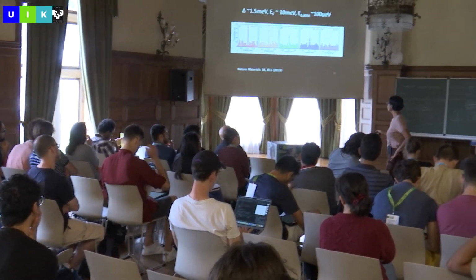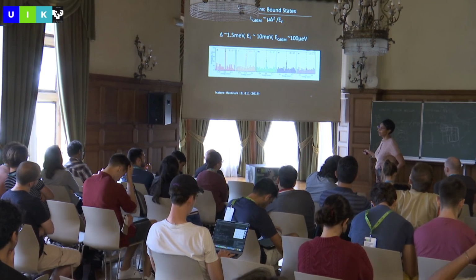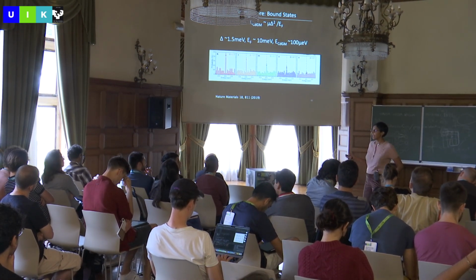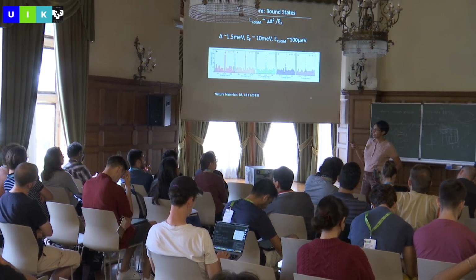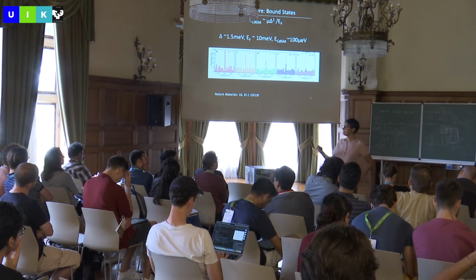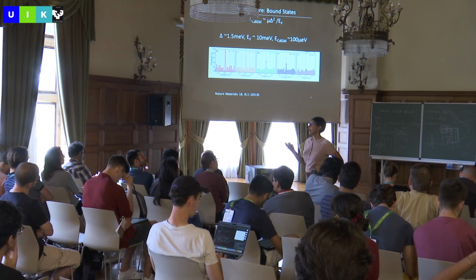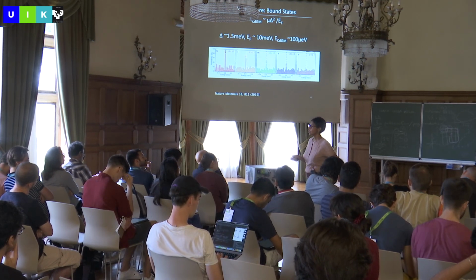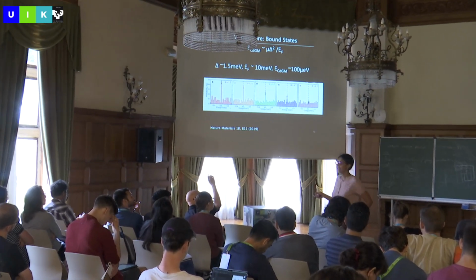So what they found was at not very low magnetic fields, fields like 1 Tesla, 80% of the vortices showed zero bias peaks, okay? And then as you increase the magnetic field, the number of vortices that show zero bias peaks goes down. That's why in the first study, only 30% of the vortices showed zero bias peaks, because they were looking at higher fields. In any case, yeah?